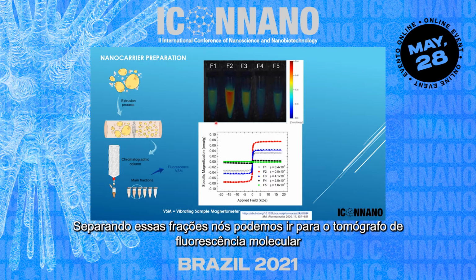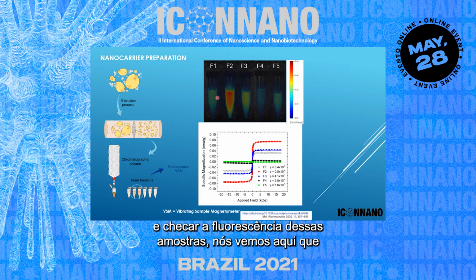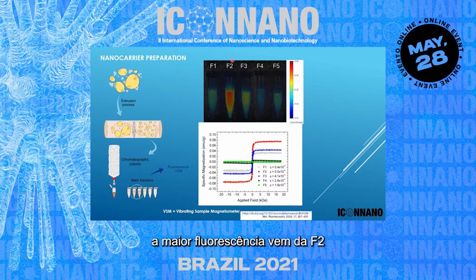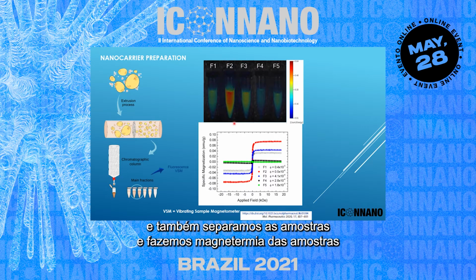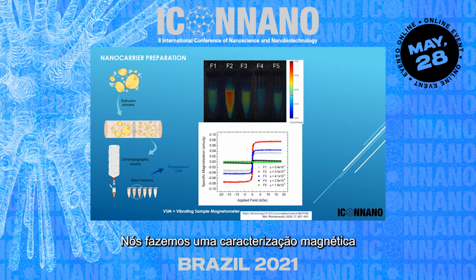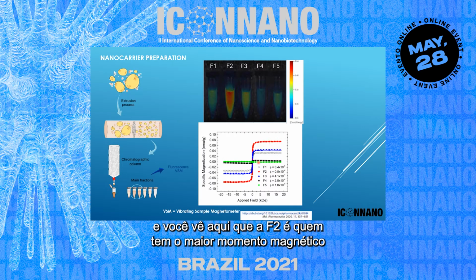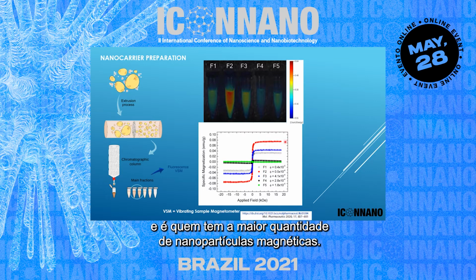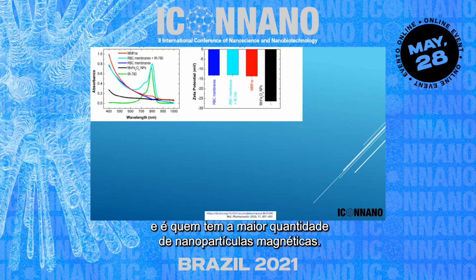Separating these fractions, we can go to the fluorescence molecular tomography and check for the fluorescence of those samples. So we see here that the highest fluorescence is appearing for F2. And we also separate the samples and do vibrating sample magnetometer, so we do a magnetic characterization. What you see here is those fractions. So you see that this F2 is the one that has the highest magnetic moment. So it also has the highest amount of magnetic nanoparticles inside.